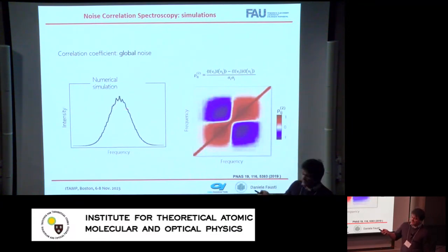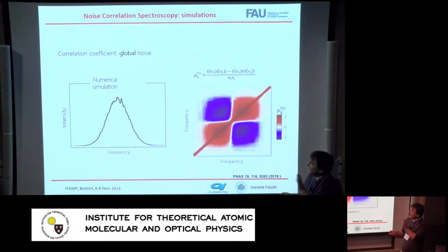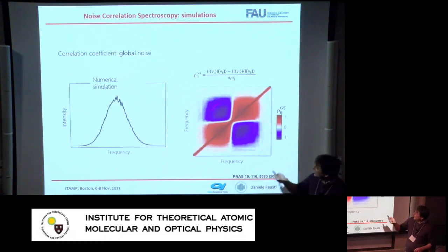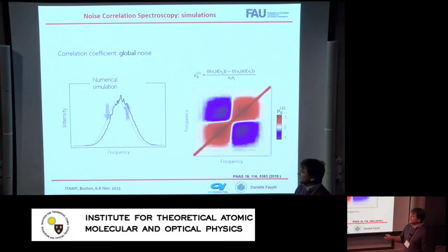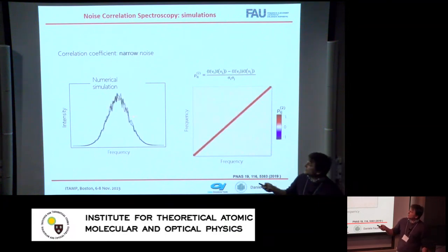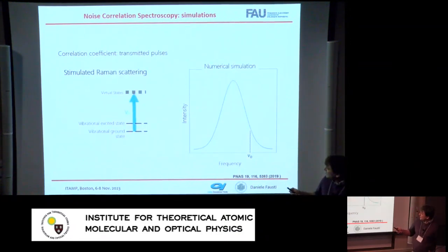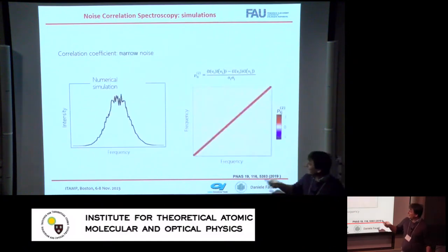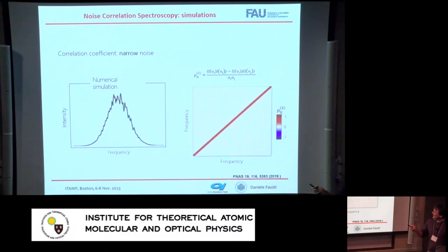On the other hand, if I have frequency fluctuations, a frequency jitter in my laser, I do have correlators which are a little bit more complicated, but are also relatively easy to understand, because if in one realization, spectral components on the right are above the average, spectral components on the left will be below the average, therefore I have negative correlations between spectral components. And the most interesting situation is one in which I have frequency uncorrelated fluctuations, fluctuations which are actually local in frequency, where essentially the fluctuation in one given spectral component correlates only with itself.